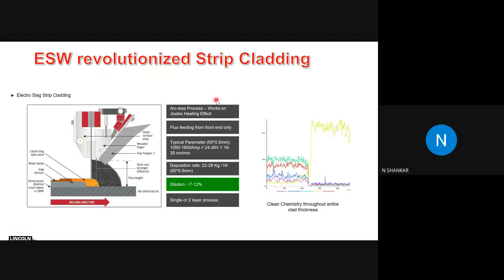And flux is required only on one side, and you can travel with a very high current of 1000 plus amps, even up to 1600 amps, with the same 20 to 22, 24 to 26 volts, and you can travel at very high speed of 1.6 meters to 3 meters per minute. You're looking at a deposition rate more than doubled, 20 to 25 to 28 kilograms per hour, which means more overlay per hour, and dilution rate is 7 to 12%, which means you get much better